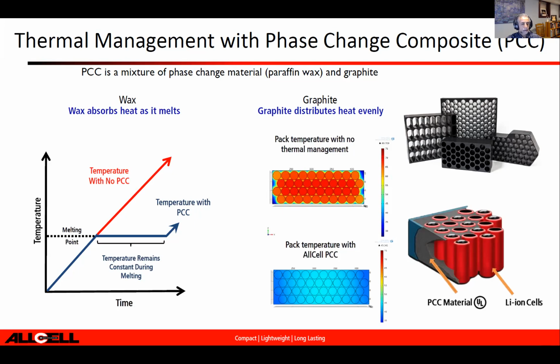That one-two punch, which is the graphite moving the heat and the wax absorbing it at the preset temperature, provides you with a passive thermal management that is actually elegant, but can be fine-tuned toward diverse chemistries or temperatures that you need. In most cases, you can do it on its own, or with a very little air system that you can add for extreme conditions, supplementing the passive thermal management system, but it's going to be much less complex and much less expensive.